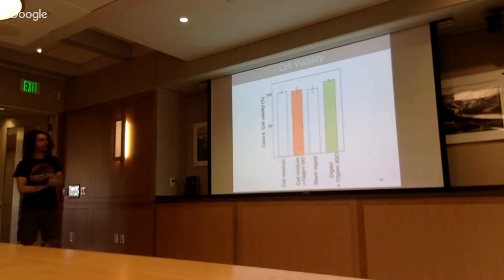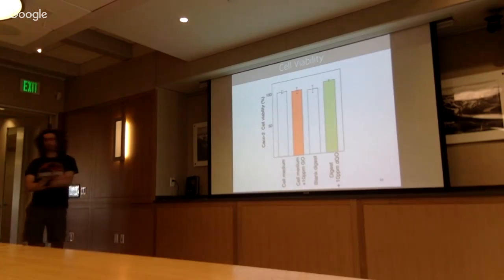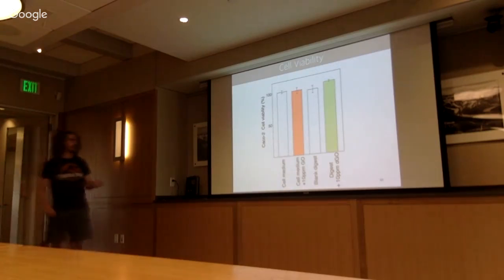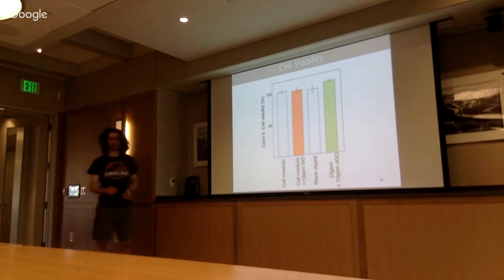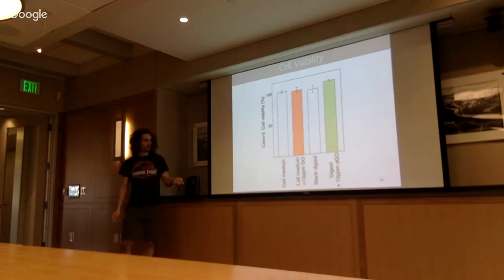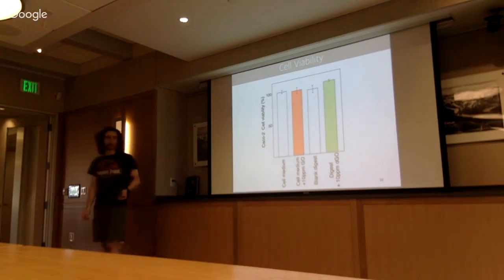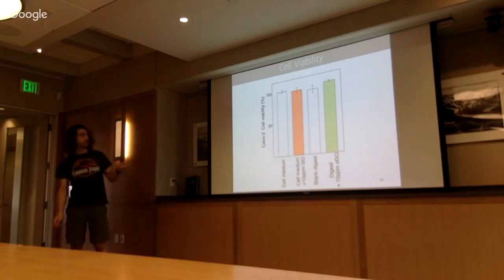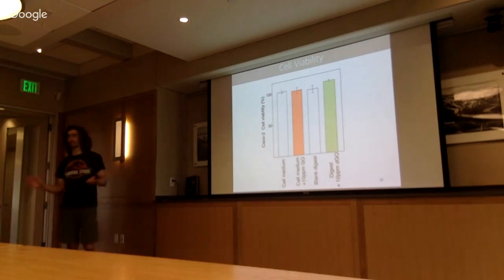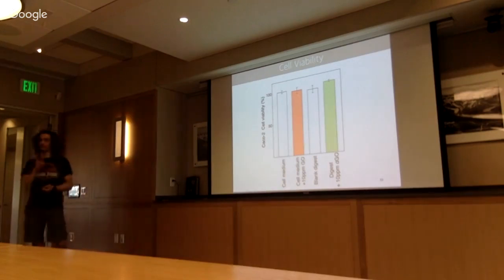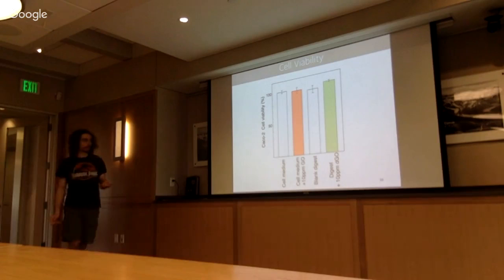So then what we did, we checked cell viability of epithelium cells. The white histograms are just controls, so you can disregard them. Here, we took the control cell medium with 10 ppm of GO. And actually, the cell viability is about 100%. So we didn't observe any meaningful biological process going on here.